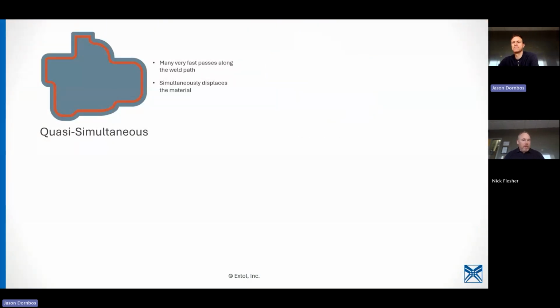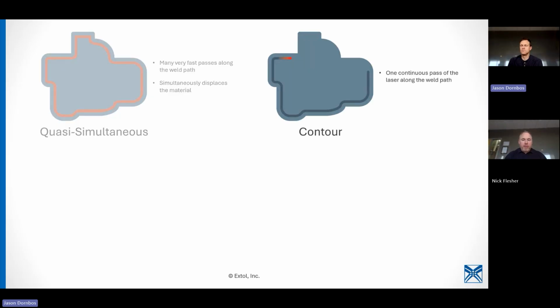So we just want to highlight very quickly, when you hear laser welding, that's a pretty broad category. Most of what we do is quasi-simultaneous. That is one laser source. It could be anywhere from 50 watts up to 750 watts. We find that most plastics, you can do degradation when you get above that. You can accomplish quite a lot with scan speed and power, but that's pretty much the most that we put in. And it's tracing a part really, really fast. And that way you're heating that surface up all at one time.